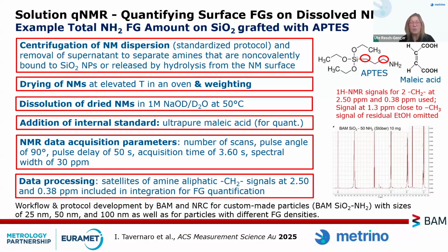So what we did here first, we had our particle dispersion. We removed the particles by centrifugation. Then we dried the particles at elevated temperature in an oven, weighed the particles, dissolved the particles in sodium hydroxide and deuterated solvents, naturally added the internal standard, ultra-pure maleic acid, for quantification, did the NMR measurements following refined protocols: a number of scans, pulse angle, pulse delay. You had to make sure that your pulses properly go back to zero, spectral width, such things matter. Then you do data processing, consider your satellites.